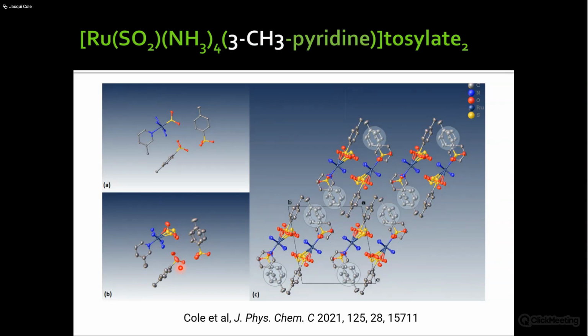That's probably because there's some steric effect going on. And this is the packing diagram. I just highlight the arene rings here because, as you saw in the cartoon earlier, these things get really very close around this reaction cavity, a lot closer than it maybe shows by eye. The arene ring of the tosylate often rotates to alleviate that strain. But not all of them have to rotate, it seems, and we learn this empirically. This is not something that we have yet been able to properly model, but this is really us learning from real experimental data as we go forward.